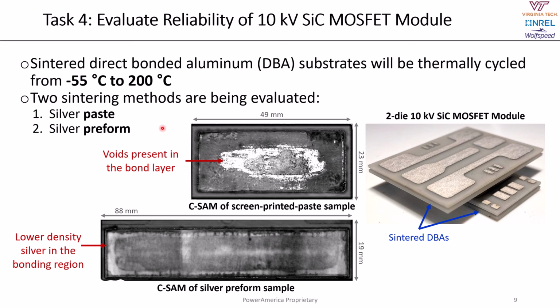We're currently evaluating 2 sintering techniques. The first uses silver paste, which is screen printed and then dried on a DBA, and then the 2 DBAs are sintered under pressure together. As you can see from the CSAM image, we do have some large voiding in the center of the large area sintering bond. So we've also been evaluating another method which uses dried silver film, or preform, which is stamped onto one of the DBAs. The 2 DBAs are then put into a hot press and sintered under pressure. As you can see from this lower CSAM, there is a significant reduction in the voiding compared to the paste method.